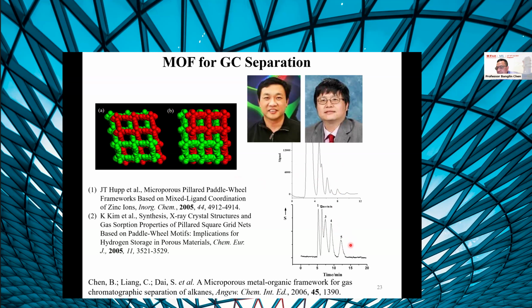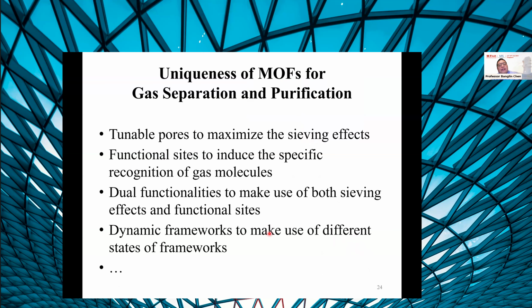The mechanism is very simple. The longer the linear part of alkane, the longer in depth the recognition with this porous material, and then the stronger interaction, the longer retention time. So that work motivates us to study MOF material for gas separation, because as a reticular chemistry, we can easily tune the pore size for sieving separation. And sieving means the material can allow small gas molecules to go through the channel while blocking a little bit larger molecules.